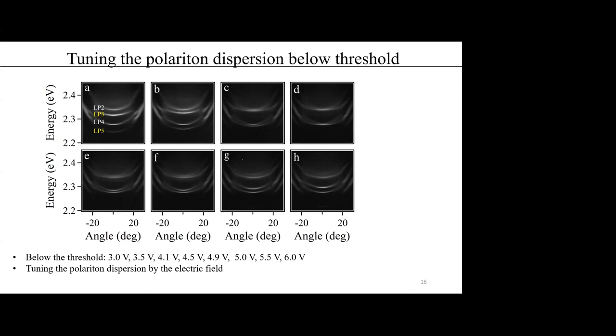When the two lower branch polariton branches with the opposite parity and also orthogonal linear polarization come into resonance at the voltage of around 4.5 volts, the Rashba interaction will shift the two polariton branches apart along the Kx direction. When the voltage is larger than 4.5 volts, we can see that the two branch polaritons are split again.